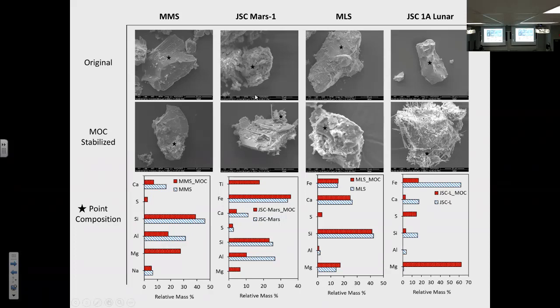So when you look at the MMS sample, which is the first column, we see that there's some accumulation of more platey structures, and I'll show you another slide which zooms in on this image. So we saw more platey, sheet-like structures being assimilated on the surface. Whereas for the MLS sample, and the lunar samples, we saw more needle-like structures. These needle-like structures were very prominent in the JSC 1A lunar sample, which is the last column.